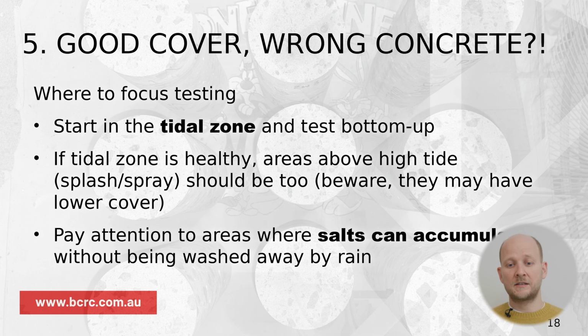And where you should focus your testing? Of course, start with the tidal zone and test bottom up. If the tidal zone is healthy, other zones will be healthy too, but be aware other zones might have lower cover sometimes. And pay attention to the areas where salts could accumulate. It does require some experience to understand and see these zones. As a rule of thumb, look at the zones which are not getting rain washed.